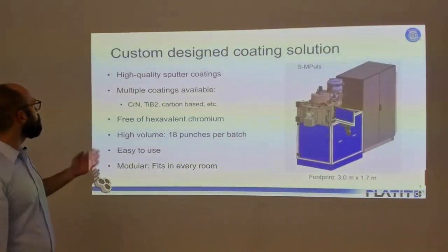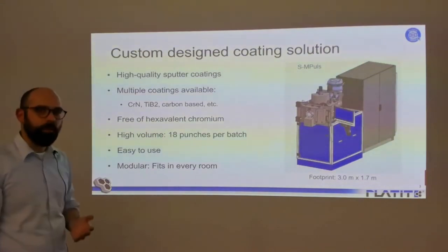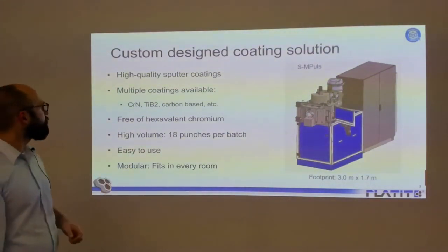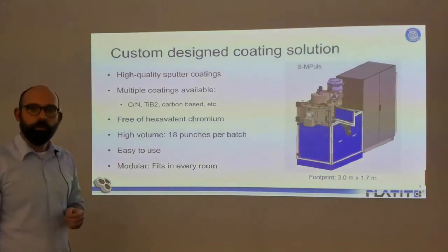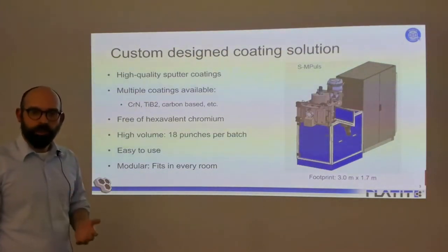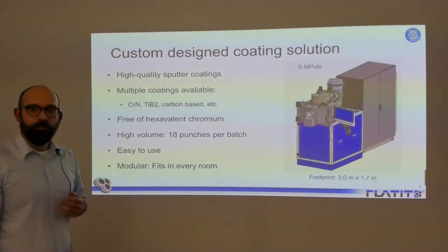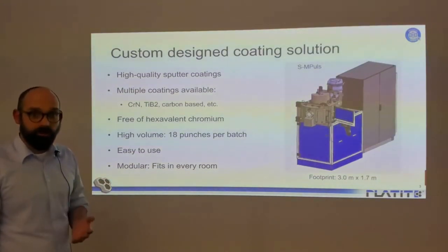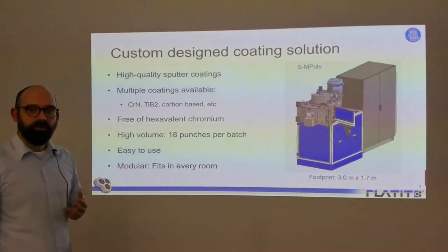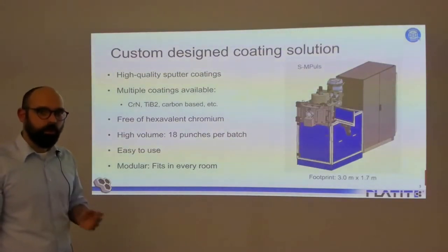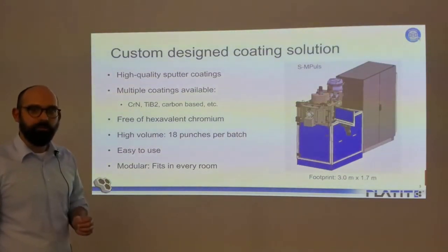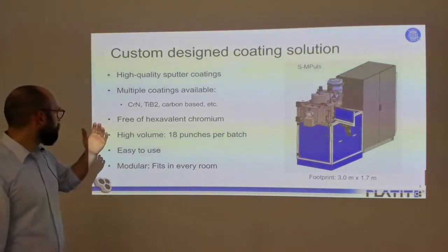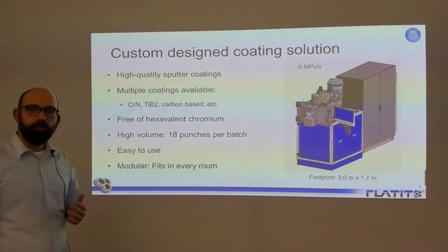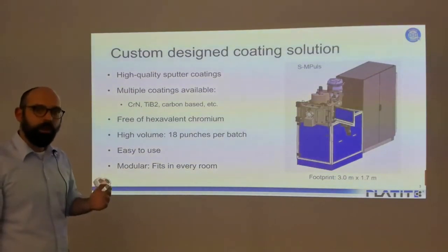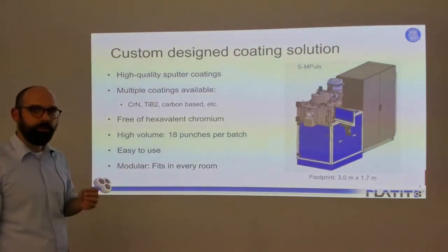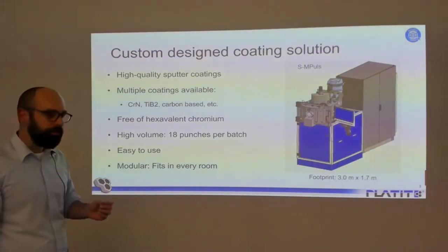The S-MPuls is our new custom designed coating solution for coin stamps. It produces high quality sputter coatings, and we have multiple coatings available for you. Chromium nitride, titanium diboride, which is a purely ceramic coating, carbon-based coatings, and of course, we develop specific coatings upon customer request. All coatings are free of hexavalent chromium. You can coat high volumes in this unit. It is capable of coating up to 18 punches within a single batch, which guarantees you a very good productivity.